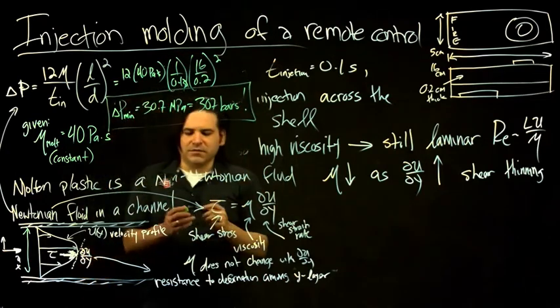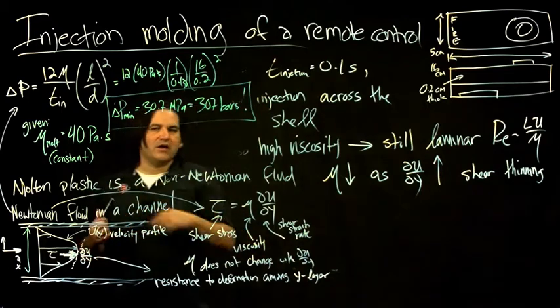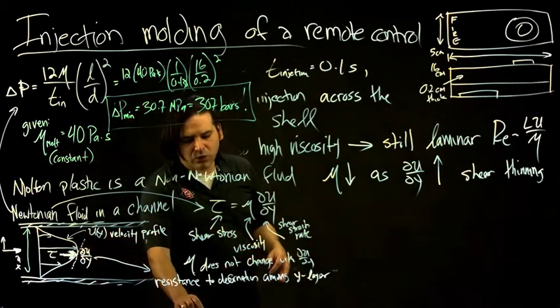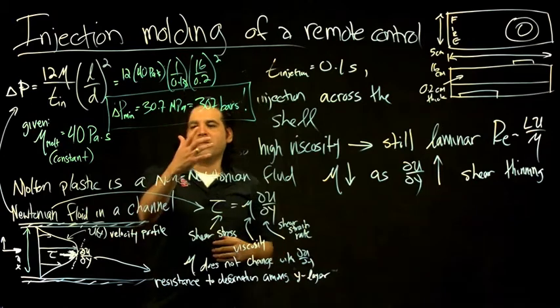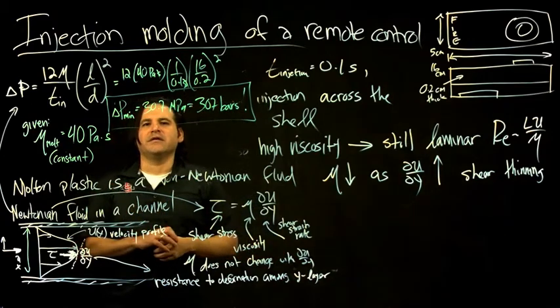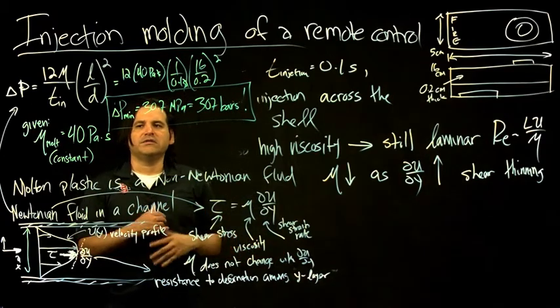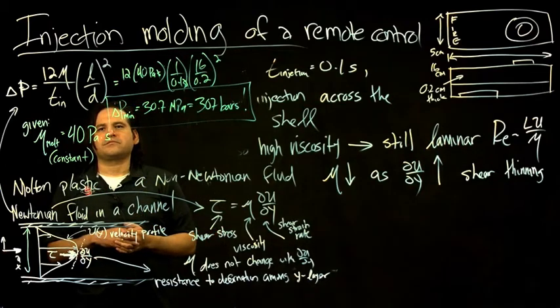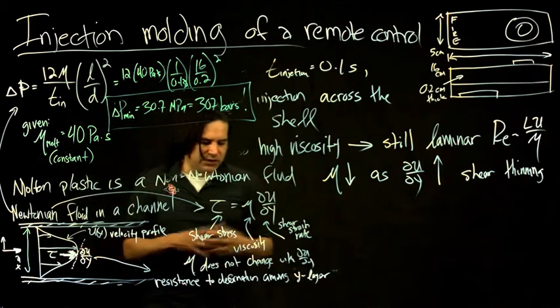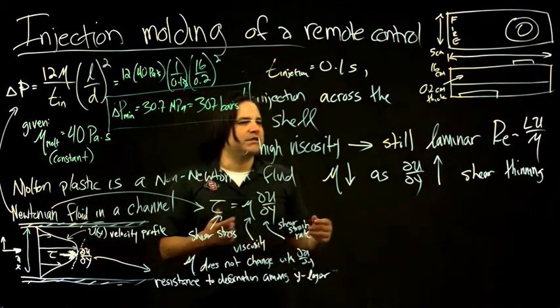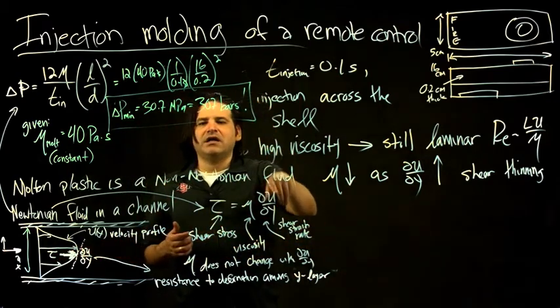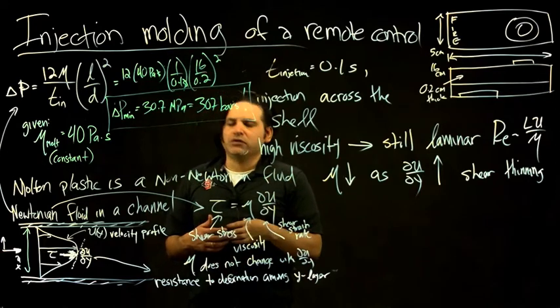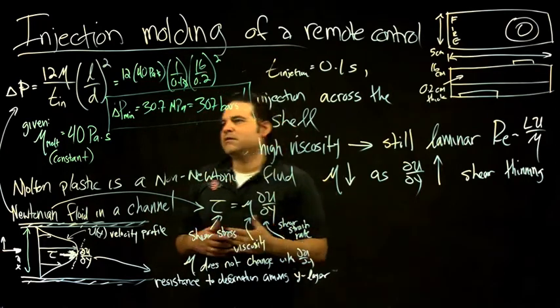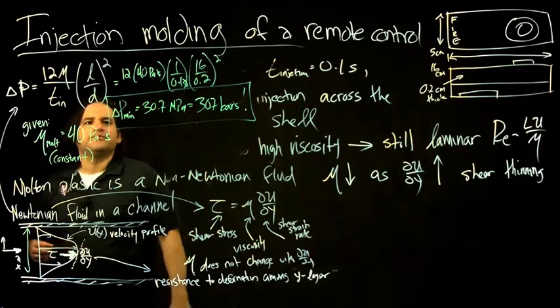The minimum is 307 bars. Right now, we're sitting in a room of 1 bar, 1 atmosphere. So we have to get the pressure 300 times bigger, a pressure difference 300 times bigger than room ambient pressure, which is huge, but that's typical. And that's because it's highly viscous, and we want to inject it quickly with this short time.